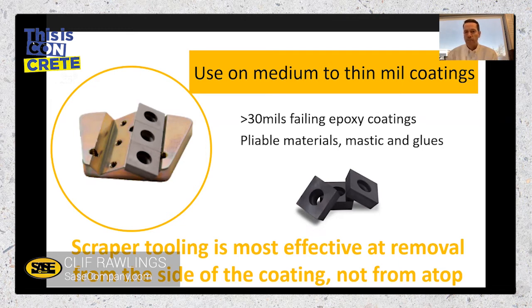Now, they're not friends of bolts and screws and stuff in this lab, but as far as removing glue, I mean, this is carpet glue. If you run into carpet glue, this is, gosh, it should be the first thing you try. It is. It's an awesome tool, especially if, let's say, the spec calls for a Class A or even a Class B finish. They don't want to see aggregate. This is a good go-to because you're not going to cut deep below it, and you can start with a higher grit after this and not expose aggregate if that's what the customer doesn't want. For example, we've used these on glue before. Have you run into people using them?